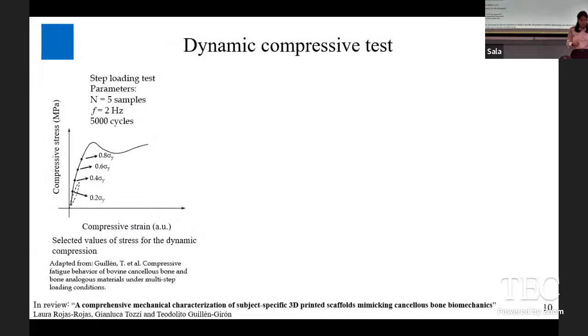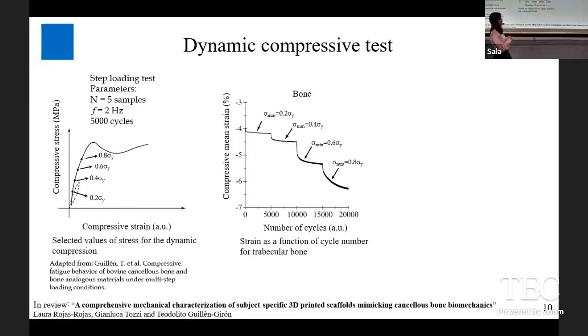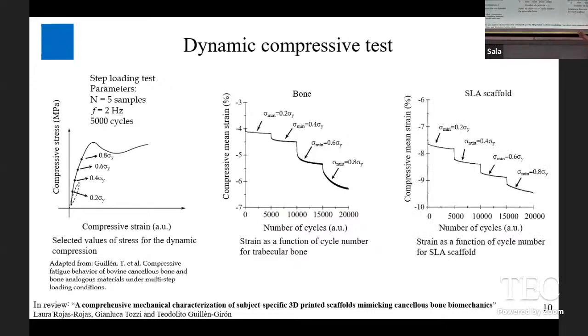Also, we did the dynamic compressive test because we wanted to see how the scaffolds behaved under cyclic loading. We chose to use a step loading procedure in which we increase the loading each 5,000 cycles, because this allowed us to test more samples. And here you can see the results for bone and for this scaffold that we fabricated.